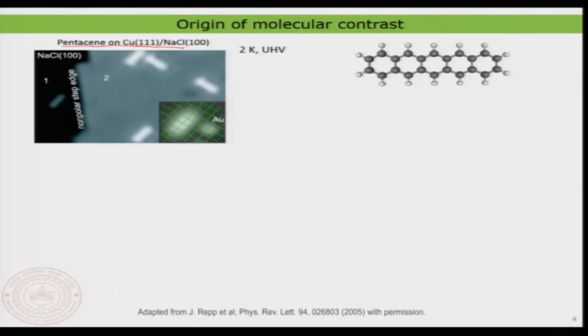But now, we are going to look at a few examples to understand this scenario better. I have here again pentacene on the copper 111 surface. I have already shown you this molecule. It is quite celebrated within the semiconductor and thin film industry. In the experiment, the pentacene molecules are deposited isolated at a very, very low dosage, which means the coverage is very low.